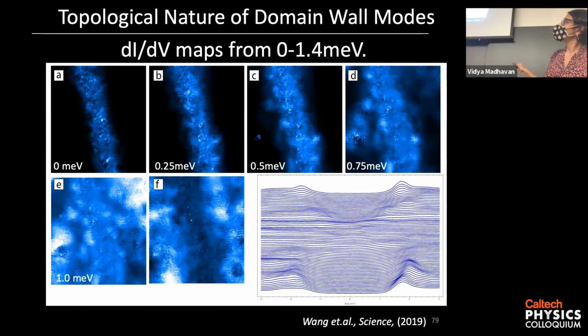This is the domain wall. And so at zero energy, you can see a nice localized mode. And as you increase your energy, the spatial extent of the mode grows. And so eventually, close to the gap edge, this mode has in fact merged with the bulk. Okay, so that's what we see.